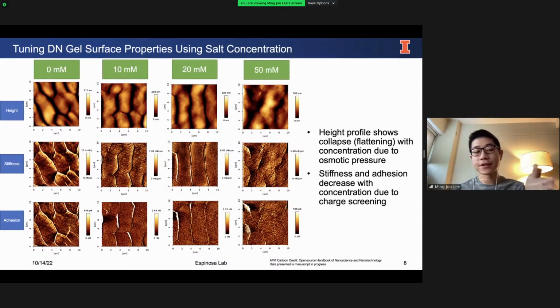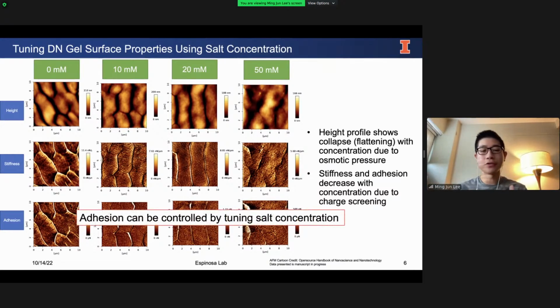Next, let's look at the stiffness and adhesion channels. The stiffness and adhesion are also generally decreasing with the increase in salt concentration. And I believe that this is due to charge screening. And I'll talk more about charge screening in the next slide. Importantly, what I want to show you with this series of AFM images is that adhesion of hydrogels can actually be controlled if we tune the salt concentration that we immerse them in.